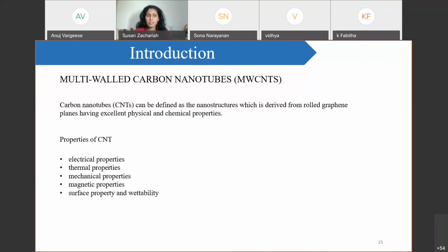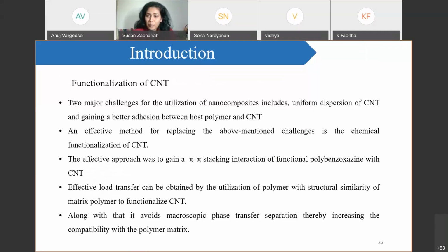So here we use multi-wall carbon nanotubes. The properties of CNT are good electrical, thermal, mechanical, and magnetic properties, and it has good surface property and wettability. The main problem in using CNT is its dispersion. The carbon nanotube is in nanoscale, so it will agglomerate together if we try to coat it. So the first challenge is how to disperse CNT, and it should also get better adhesion with the host polymer. These are the two challenges: dispersing it properly and getting better adhesion with the host polymer matrix.